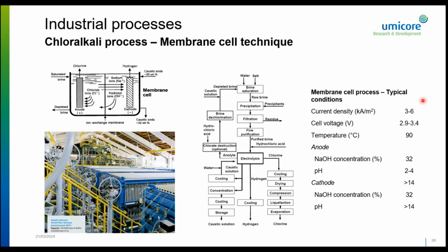Here are some process conditions, not that important, but as you can see, the current density, which we always like to compare, is very high. Let's say at least about 10 times higher than the ones that we typically see in electrowinning. And as I said, current density is a measure for the production rate and also for the size of the facility you need. Because if you have higher current density, you get a higher production rate, and you can go to a much smaller production facility.